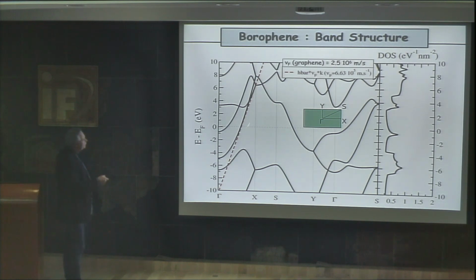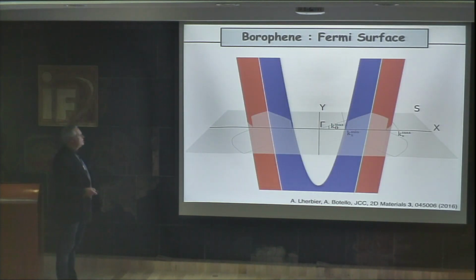We can also calculate the Fermi velocity for the charge carriers at the Fermi energy, and we see that we are at 6.6 times 10 to the power 5 meters per second, which is about one quarter of what we can obtain, for example, in the case of graphene. So this means that it's normally a very good metal, this borophene.